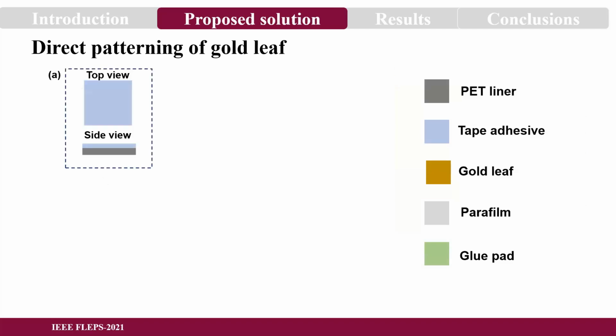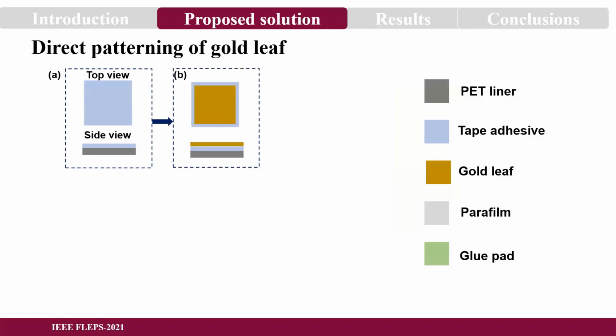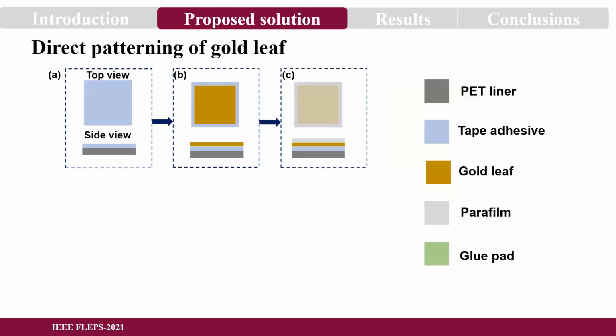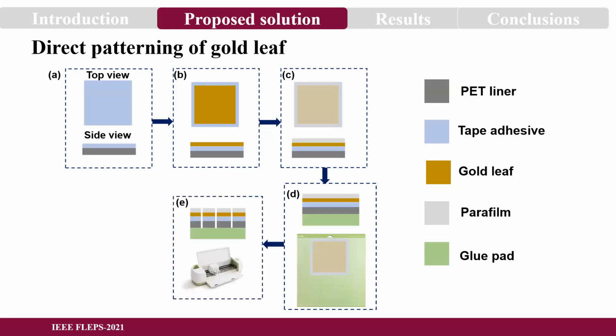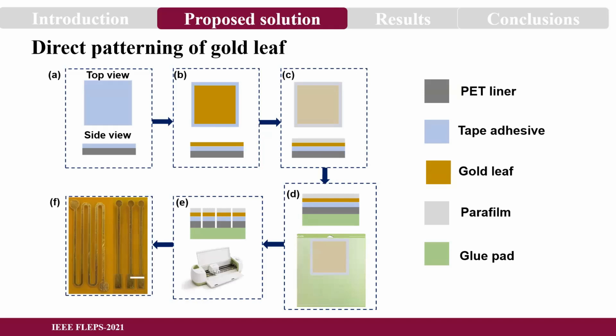So here we propose a direct patterning method for gold leaf. To start with, we generally use a single-sided tape to fixate our gold leaf. Once the gold leaf is fixated, we cover its surface using Parafilm, which protects the gold leaf when we pattern it using a benchtop tabletop cutter. It's also a low-cost cutter, which can be bought for somewhere close to $300. And finally, this method can be used to generate different patterns, like curves, as shown in the picture.